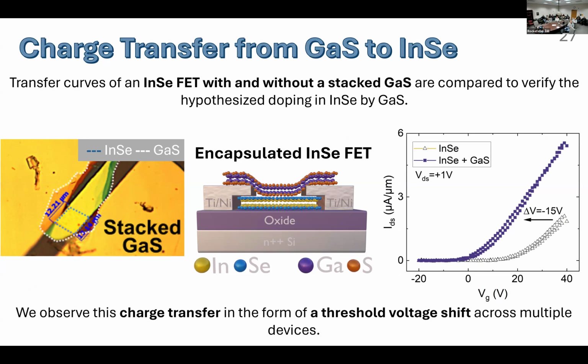If you remember, we can obtain the amount of carriers participating in the conduction at any given gate voltage. So if we look at 30 volts, for example, the number of carriers participating in conduction is much larger in the heterostructure than in the indium selenide, suggesting charge transfer from the gallium sulfide into the indium selenide layer.